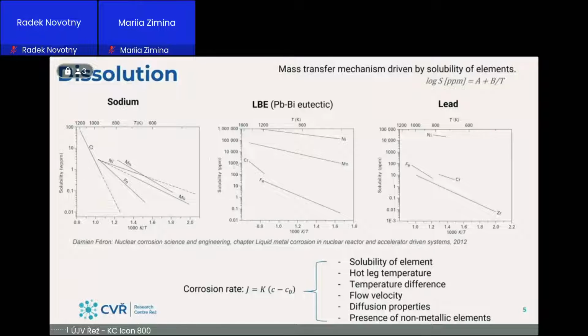On the opposite side, there is lead bismuth eutectic alloy that has very high solubility of nickel. You can see there is 1 million ppm or something like that. That means that there is a problem with this mass transfer. And in lead, this situation, let's say, is 1 order of magnitude better.